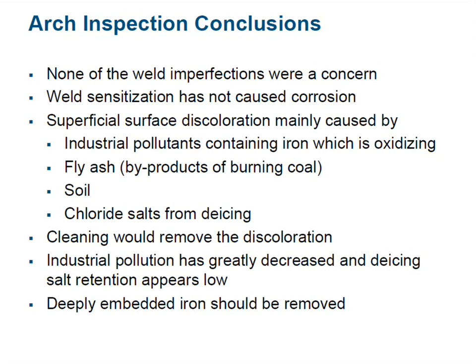None of the weld imperfections are a concern. There were some, but nothing at all a problem. The weld sensitization has not caused corrosion. So again, no problems. The surface discoloration is superficial. It will have no effect. It's all from industrial pollutants. I think I made a joke once on site that you should send the carbon steel industry a bill, or maybe the power plants a bill. But you know, the cleaning would remove discoloration, but it is not needed. The only thing I thought should be removed was some of the embedded iron. Are there any questions?